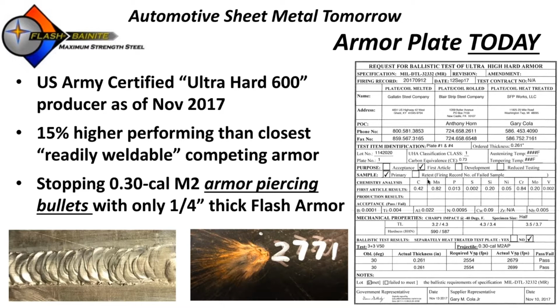Now, one thing we're doing beyond this is we're actually doing a little bit more research because we believe we can take it a step further. And in our internal testing, we are actually stopping 30 caliber M2 armor piercing bullets with only a 1/4 inch thick Flash Armor. Now they are at 30 degree obliquity, but that's because that's what the US Army spec does say. The 2771, I guess when you blow it up, it's a little bit overwritten, but that's 2,771 feet per second, which is about the factory muzzle velocity of a 30 caliber armor piercing bullet.